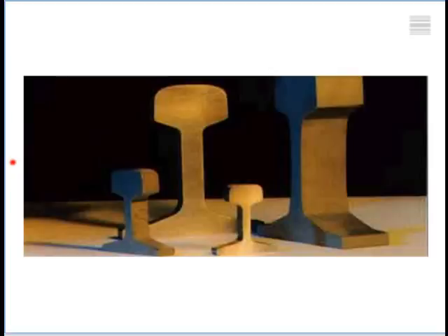These are rail steels, completely different requirements, where we want rolling contact fatigue and wear resistance, but really based on exactly the same structure as I illustrated. Now, with this, we ran up against a problem that when we started to manufacture rails which are small, there was no difficulty, perfectly happy. As soon as the process was scaled up to large, the rails started to fracture. This is even without being put into service. They would fracture while they were being stored.